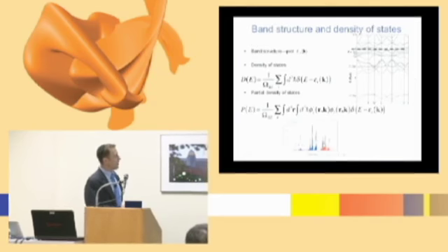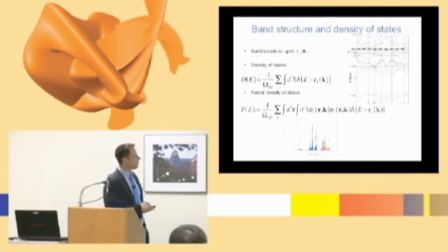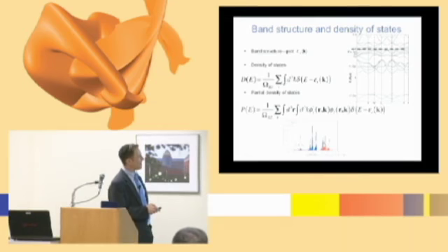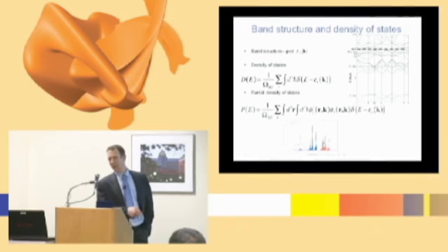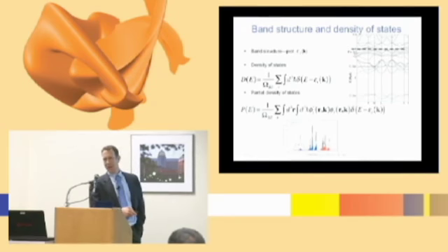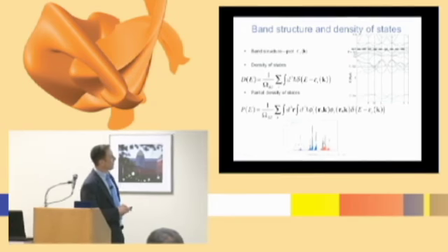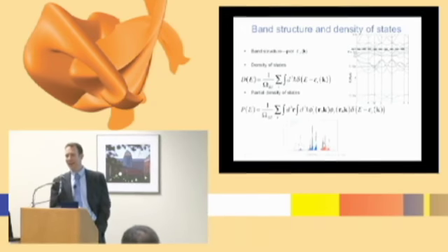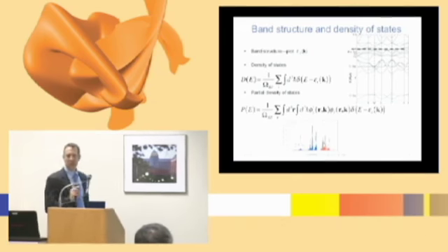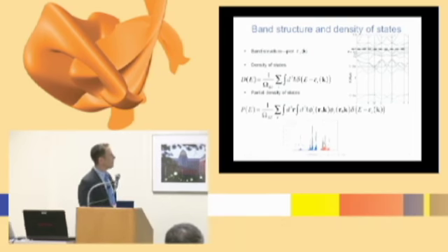After you do that, one has something like a band structure that you can get out. I said there are these different names for the different points in K-space, and you can plot the eigenvalues as a function of where they are in the Brillouin zone. This, for example, is another motivational slide for doing QMC. This shows you the computed band structure for FeO. It predicts FeO to be a metal. It's actually a good insulator. Okay, and this is no matter which density functional you use.